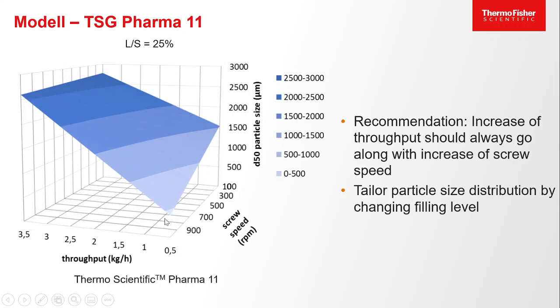You'll see that increasing the throughput will increase the average particle size, so the mean mass diameter. And this is because you basically feed more material into the screws, and by doing so, you fill up the screws more at a constant screw speed, and this leads to more compaction and larger granules. The opposite happens if you increase the screw speed, from 100 up to 900 RPM. If you increase the screw speed, granules become smaller on average, because again, the screws empty more. You have less compaction happening, and smaller granules result from that process.